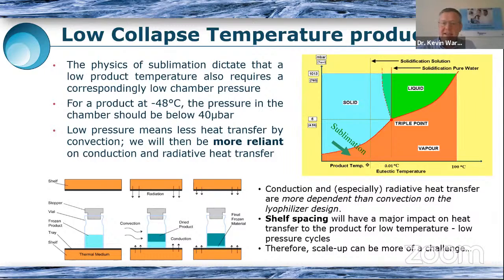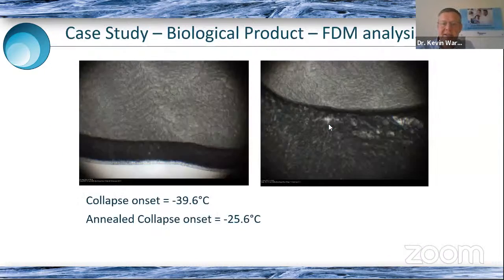So just to go on to the case study, this is from a biological product that we worked with a few years ago, and our customer approached us and said they've got a very long freeze-drying cycle, and they were keeping the product safely below -40, having established that the collapse was just above -40, and therefore they had quite a long cycle. So the first thing that we did was to say, well, let's reanalyze the formulation. And what we found was that in the initial determination, the formulation had not been annealed, so the annealed form had not been investigated for collapse. Whereas when we annealed it, we found that the collapse temperature was then -25.6 rather than -39.6. So annealing it meant that the collapse temperature increased by 14 degrees.